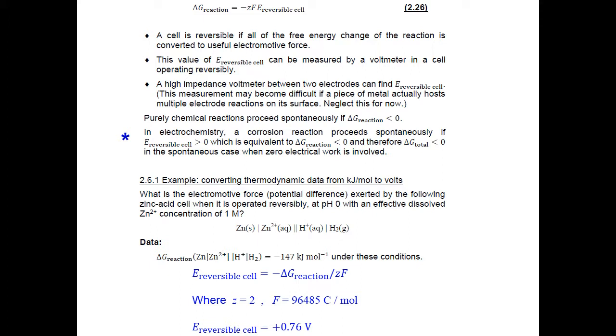The question is, how do we take that Gibbs energy change, which we're told under these conditions? The conditions are actually standard conditions, so the Gibbs energy change of the reaction is the minus 147 kilojoules per mole we presented earlier as the standard Gibbs energy change. We just use equation 2.26. E of reversible cell is equal to minus delta G of reaction over ZF, plug numbers in, and the E of reversible cell for zinc dissolving is plus 0.76 volts.